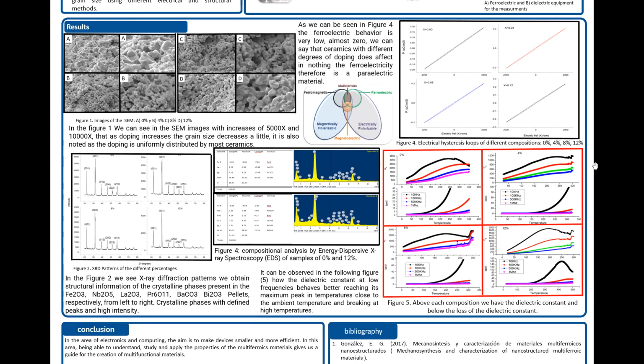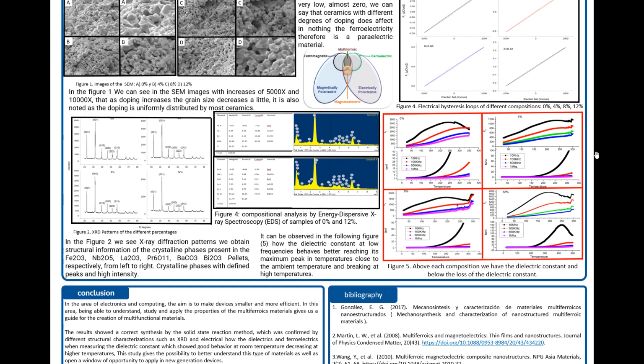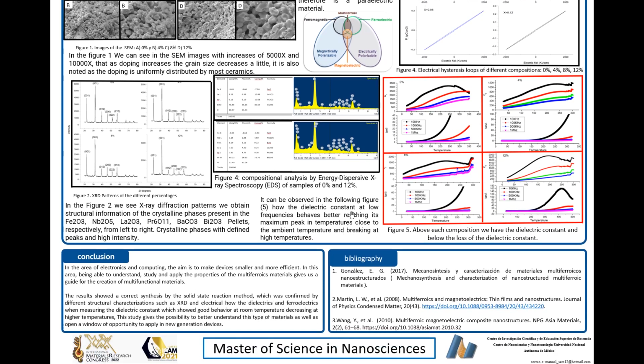After that, we do the electric measurements, and we can observe that at room temperature we have a good dielectric constant at low frequencies, and it is equal for all of the compositions. And after that, at higher temperatures, we lose in the dielectric constant. And at the end, we do the compositional analysis by energy dispersive X-ray spectroscopy, EDS, and we can observe the percentages of all of the compounds present in this material.